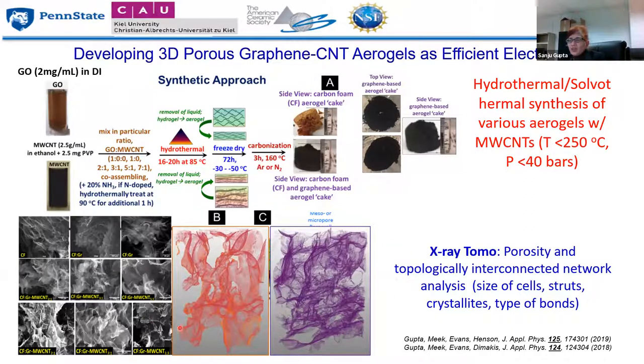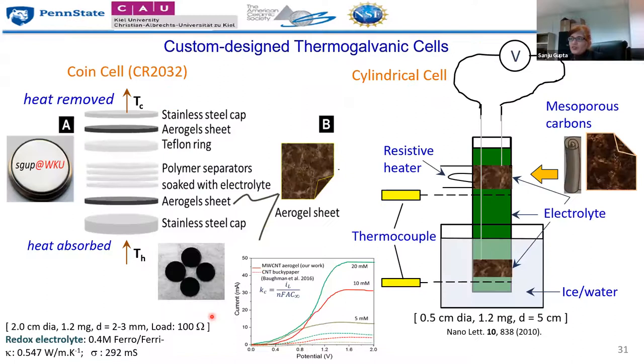And you can see here in the SEM and the corresponding computed tomography a beautiful topological interconnected network. And that's what allows us to expose as many edges and as much surface of graphene as we can, the graphene and carbon nanotubes, both of them. So this topological interconnectedness allows us faster ion transportation, more sites. And so these are some of the properties that we utilize for our thermogalvanic cell construction.